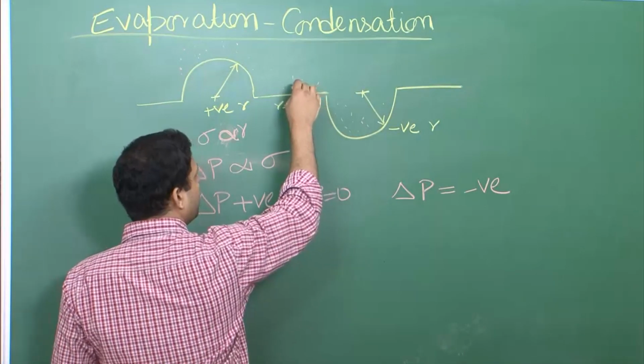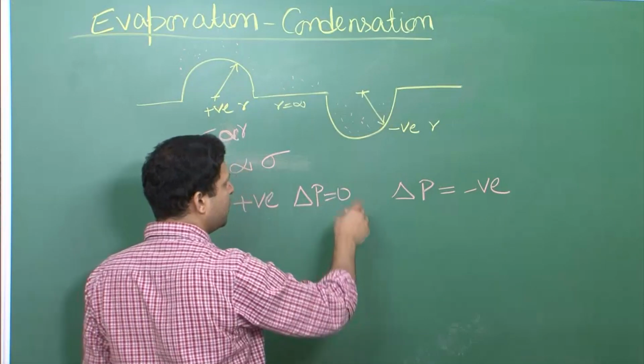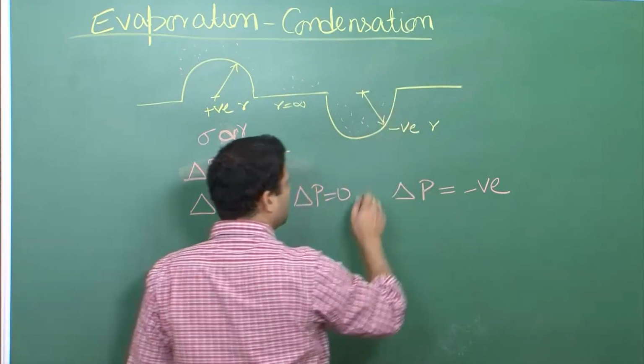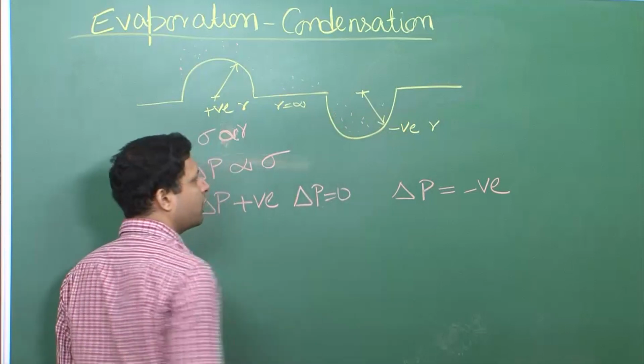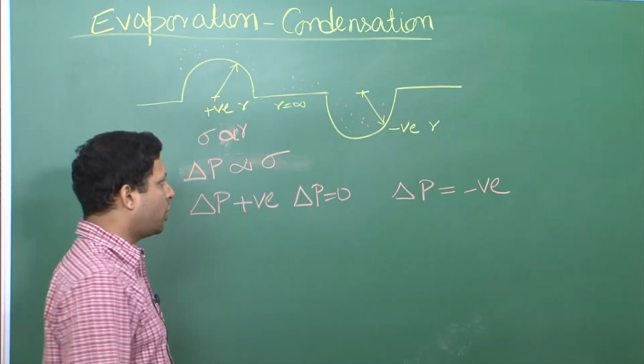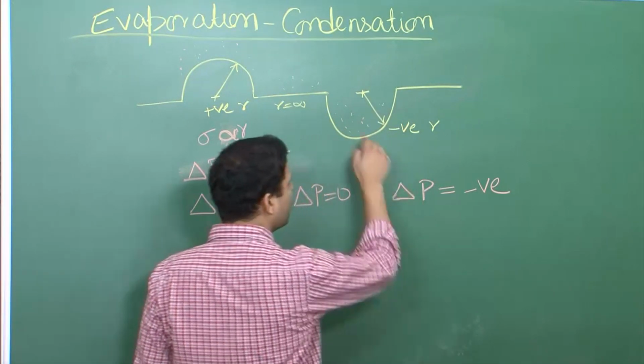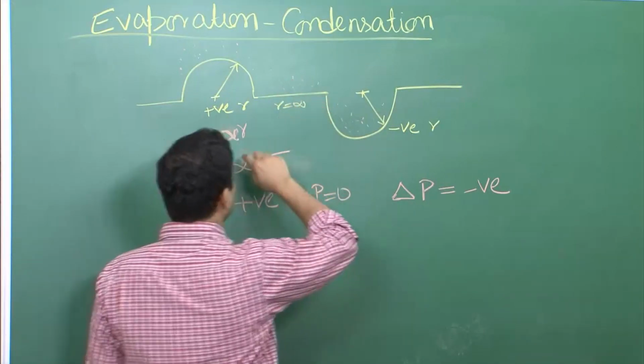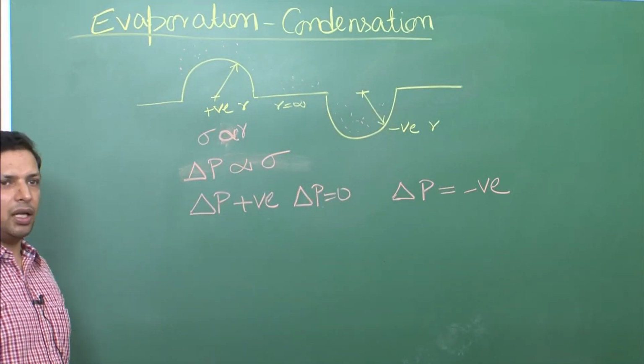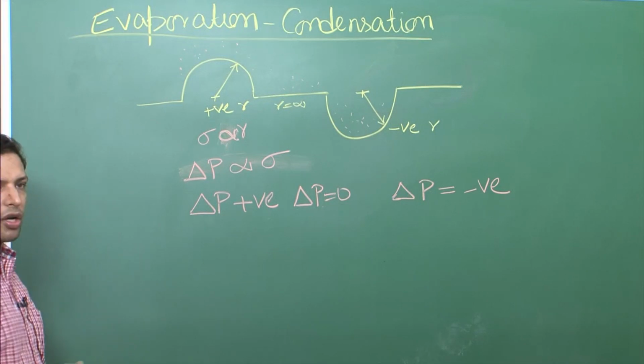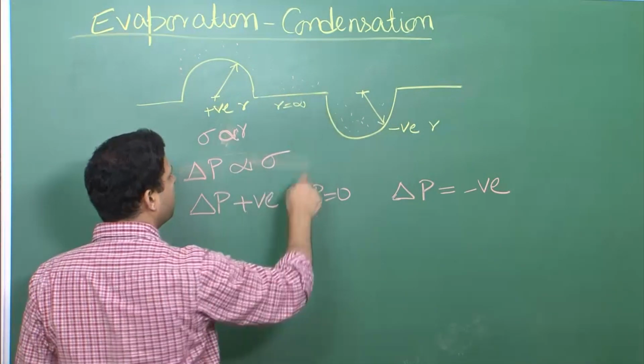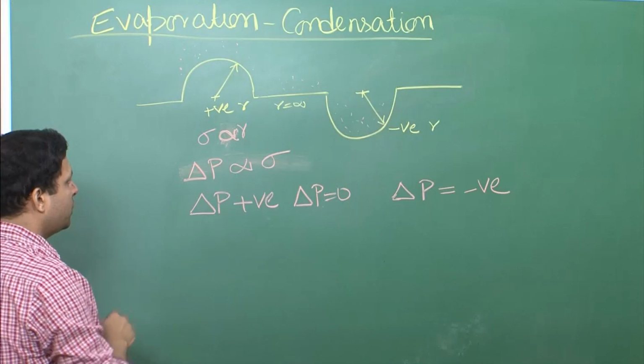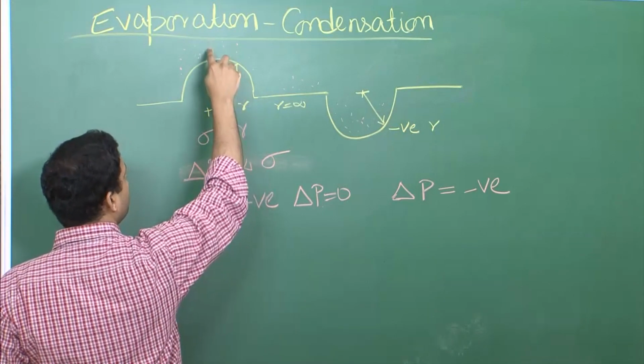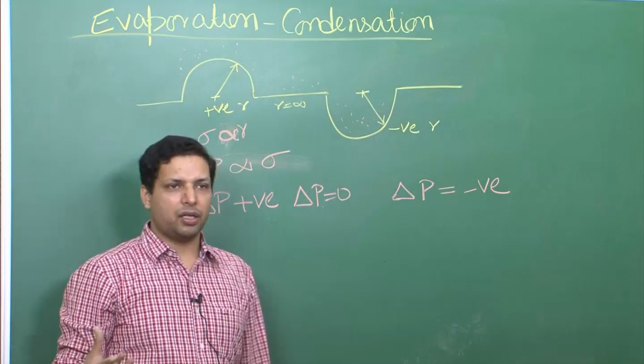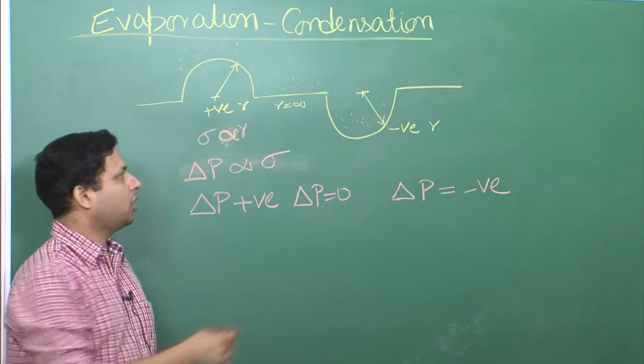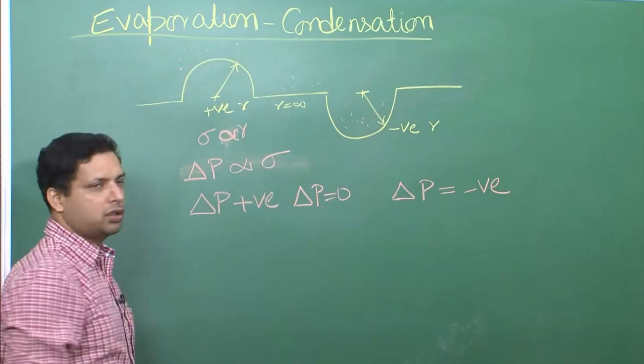Because we are comparing it with the flat region, here with respect to the flat region, delta p is equal to 0, and in the negative radius of curvature, the delta p is negative. So, delta p is lower than what you will see over here. So, we are comparing the delta p, which is the partial pressure, with respect to the flat plane. And from here what you see is that if delta p is positive, it means the amount of that particular material is very large in a region just over this.